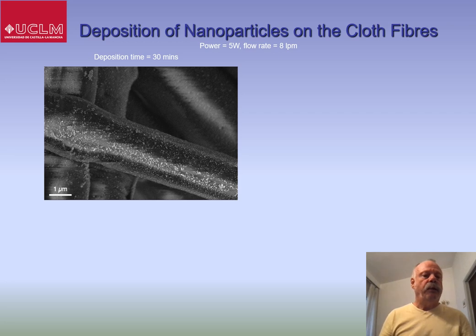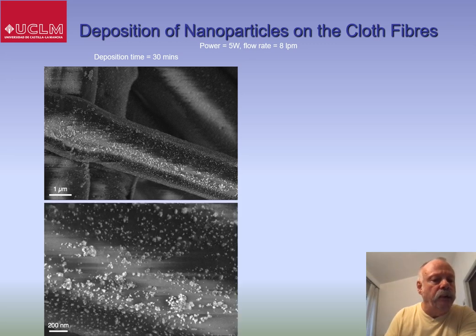Looking in more detail at the silver nanoparticles within the cloth, these are again SEM images of fibres within the cloth, and this is after a deposition time of 30 minutes with the power and flow rate shown here. And at higher resolution, you can see the individual nanoparticles on the fibres within the filter. So that's a 30-minute deposition time.